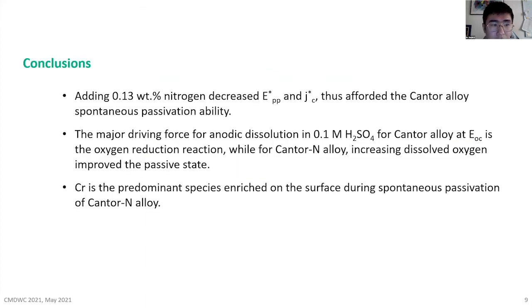So here are the conclusions. When we add 0.13 weight% nitrogen, we decrease the primary passivation potential and the critical current density, thus affording the Cantor alloy spontaneous passivation ability. And the major driving force for anodic dissolution in 0.1 molar sulfuric acid for Cantor alloy at open circuit potential is the oxygen reduction reaction. While the dissolved oxygen improved the passivity for the Cantor N alloy, and the chromium is still the predominant species during spontaneous passivation of Cantor N alloy.